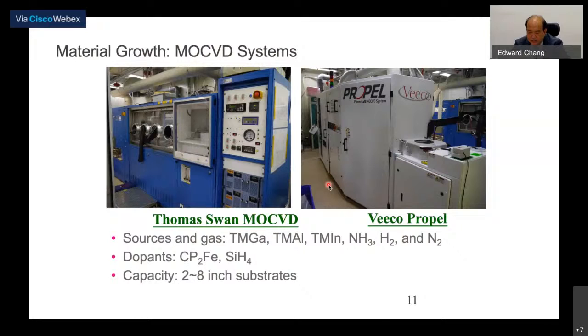Gallium nitride, to be competitive in the market, has to be grown on silicon, because silicon devices are very low price. So first you have to try to grow this gallium nitride on a silicon substrate. We know GaN has good performance, but then how about the price? So you have to grow this on a silicon base. And this is the machine we use, from Thomas Swan and Veeco Propel. We use various gas precursors to give us the source, and also some dopant gases. And usually this kind of new machine can handle up to 8 inches.